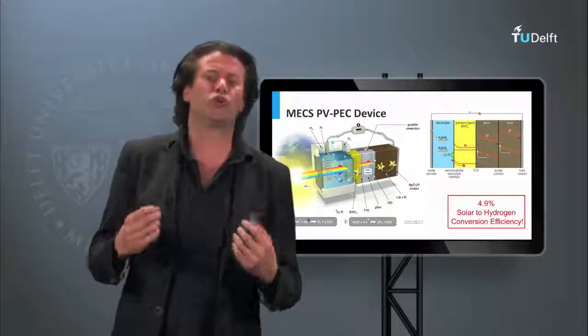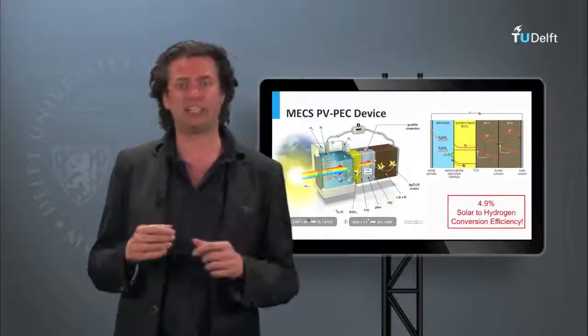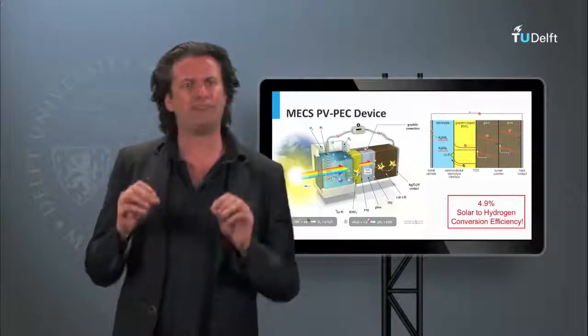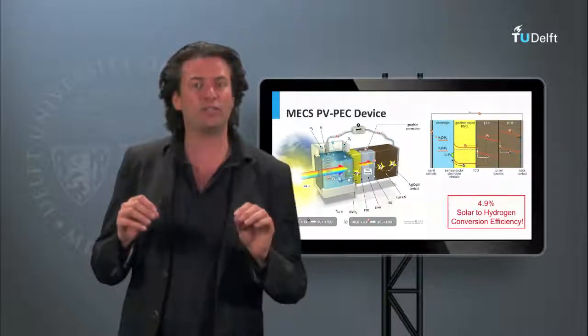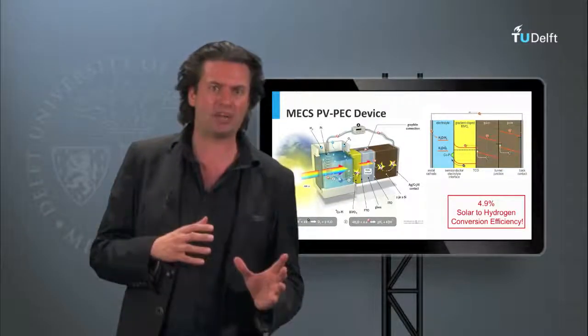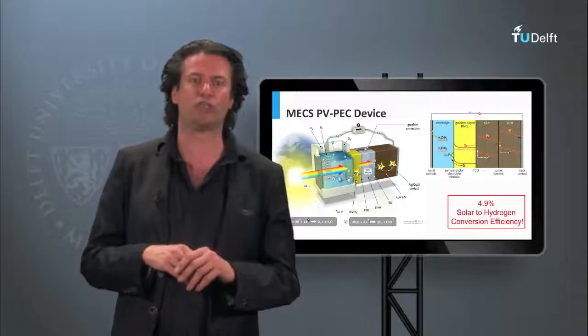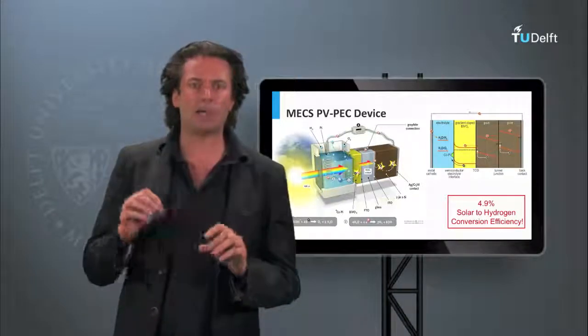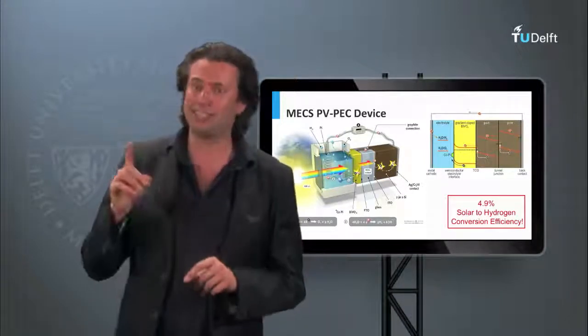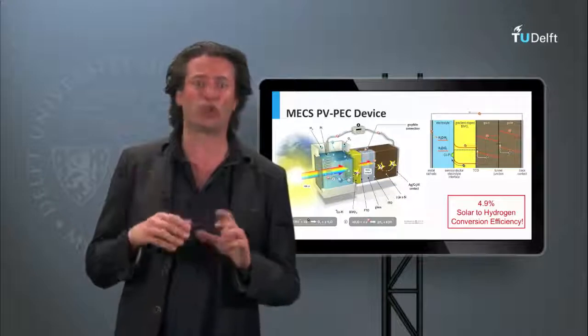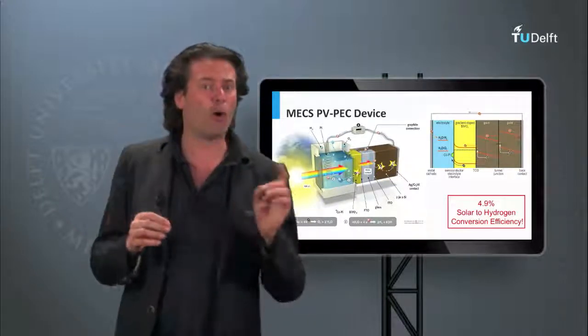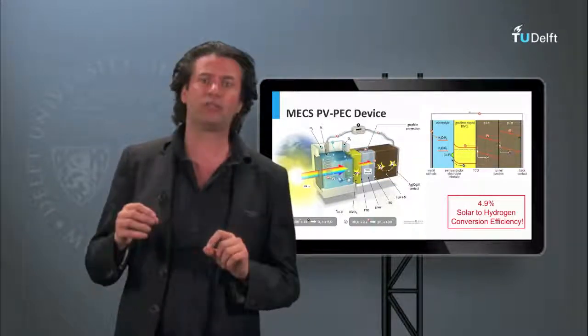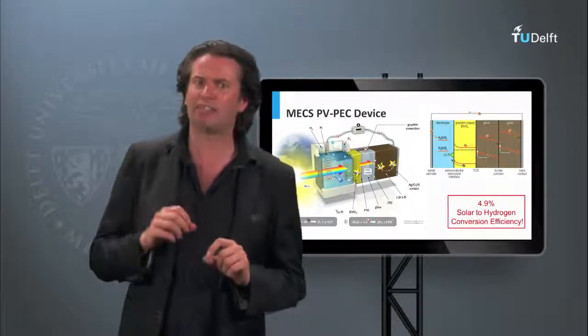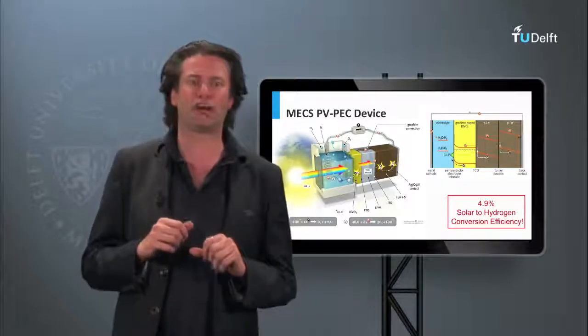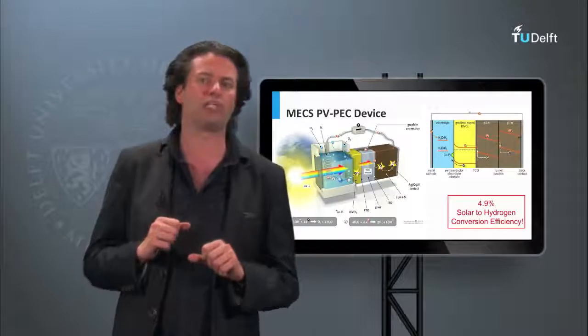Applying all those concepts, we here at the Delft University of Technology have developed a device made with a bismuth vanadate photoanode combined with a double junction amorphous silicon solar cell and a platinum cathode. This device has achieved a solar to hydrogen efficiency of 4.9%, which is actually the highest efficiency reported for such devices based on metal oxide photoanodes.